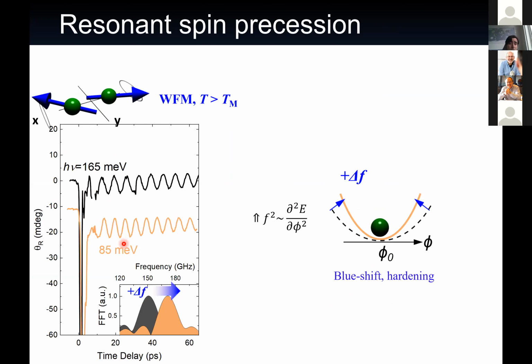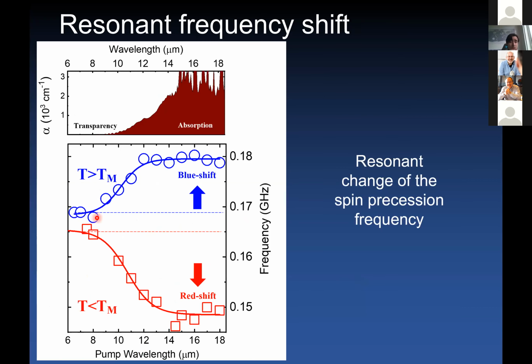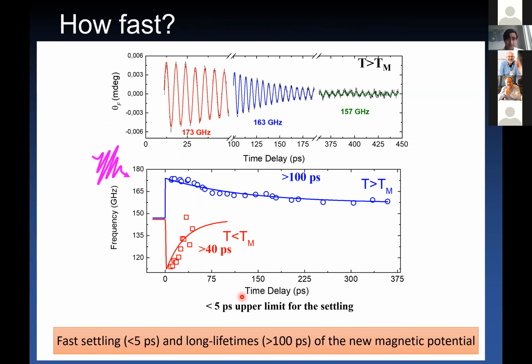This is observed in the low temperature antiferromagnetic phase. In the high temperature ferromagnetic phase, a similar phenomenon is observed. If you excite your system at resonance, you also observe a change in the magnetic potential, but this time instead of softening, it hardens. So the frequency of your spin waves is increased. Here you see the whole set of data of the magnon frequency as a function of pump wavelength. You see the blue shift, a hardening of the magnetic potential, in the weak ferromagnetic phase, and the softening of the potential, a red shift, in the low temperature antiferromagnetic phase.